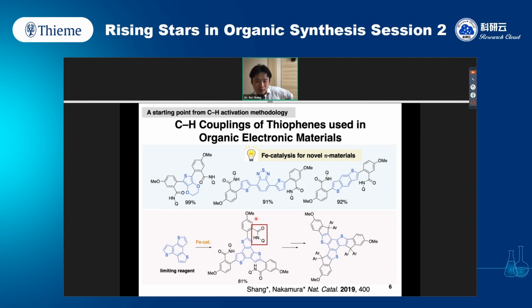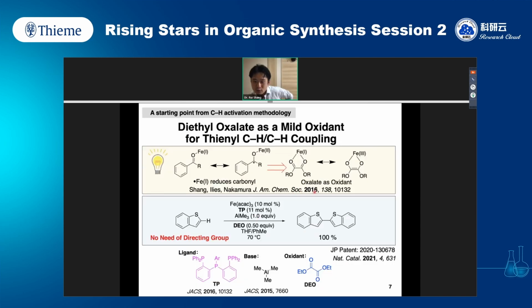Inspired by our very old results, actually from 2016 when we published the work, our discovery on carbonyl-directed CH activations. We discovered that diethyl oxalate is a very good oxidant for thiophene CH-CH coupling. The reaction uses an iron-3 salt as a catalyst, the tridentate phosphine ligand originally developed by us, and we use trimethyl aluminum as a base for deprotonative CH activation. This was also discovered originally in our lab. And critically, this diethyl oxalate is a unique oxidant.